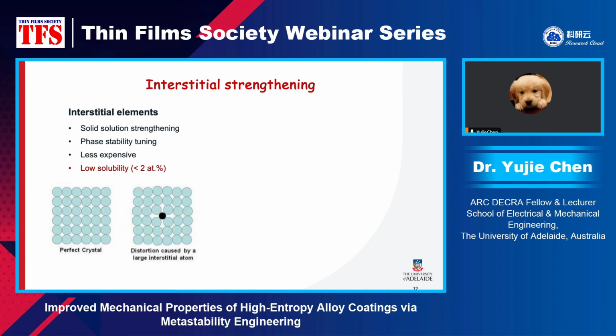However, the challenge is that interstitial elements have a very low solubility in high entropy alloys, usually less than 2 atomic percent. What's going to happen if you add more than 2 atomic percent? The problem is you are going to have brittle ceramics. This brittle ceramic precipitate starts to form, which decreases the material's deformability and makes the material brittle.